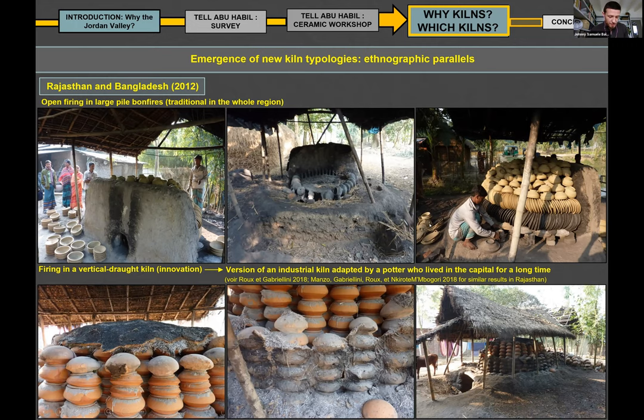But they also use a vertical kiln with the lower chamber deeply buried in the ground and the pots stacked up and piled up on the ground, covered by a layer of mud and straw, as you can see here. Indeed, this vertical kiln is not documented at all in the surroundings. And this isolated innovation is indeed just the attempt of a potter who lived for a long time in the capital, to reproduce a vertical industrial kiln. And similar results, as I said before, have been observed in Rajasthan in India.